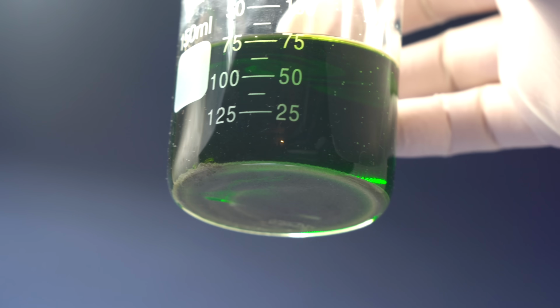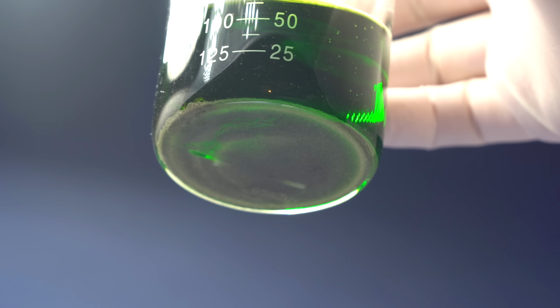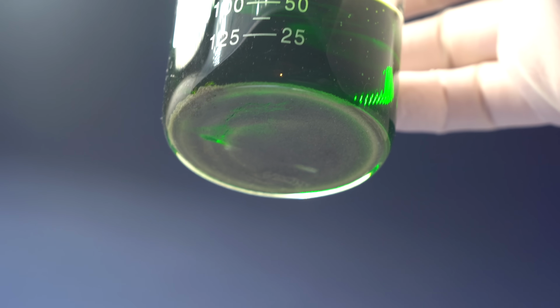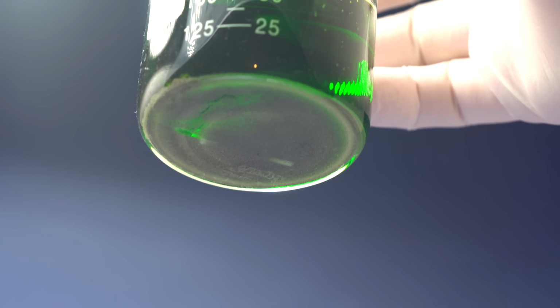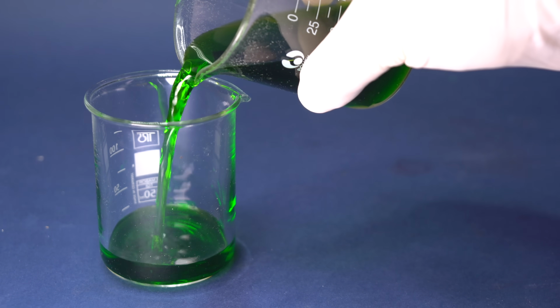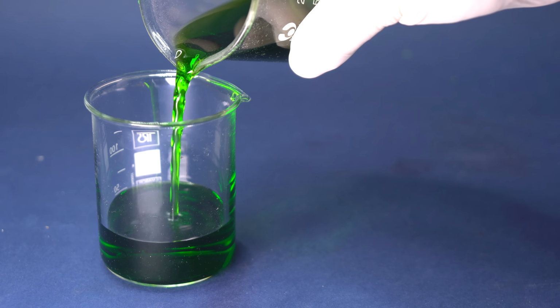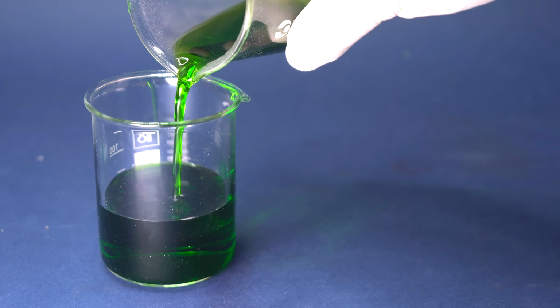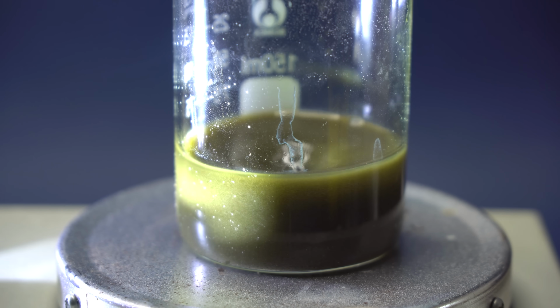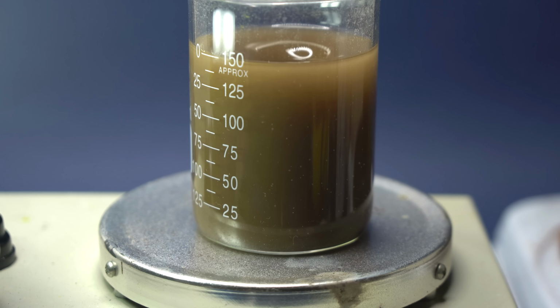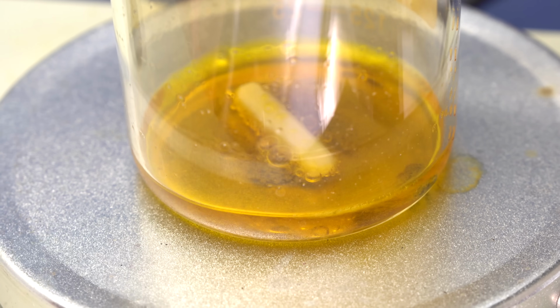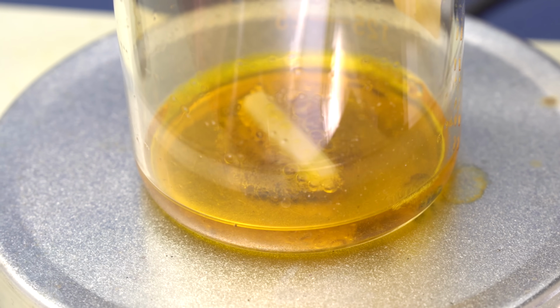On the bottom, there are some silver chloride and gold particles which have not reacted yet. We need to separate them from the rest of the solution and dissolve them too in aqua regia. I am removing the unnecessary silver chloride from the solution with the help of sodium thiosulfate, which forms water-dissolvable complex with silver chloride, and then dissolving the leftover gold alloy in aqua regia.